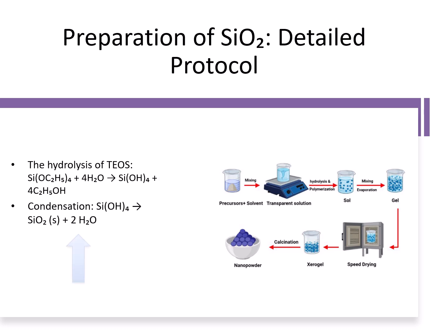Following hydrolysis, condensation occurs, where silanol groups react and release water or ethanol, forming strong silicon-oxygen-silicon bonds, building a 3D silica network, forming a semi-solid gel. Once the gel is formed, it is aged for 24 to 72 hours at room temperature to allow condensation to be completed, and afterwards it is dried at 80 to 120 degrees Celsius to remove trapped solvents and volatile byproducts. It is then calcined in air at 450 to 600 degrees Celsius for 2 to 4 hours to burn off organic residue, resulting in a silica powder of over 90% purity.